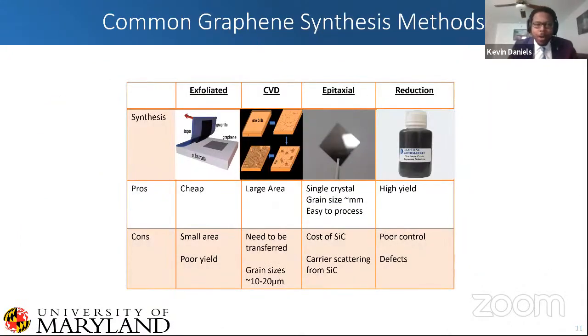Now, jumping over to graphene, because that's what we're using as a scaffold, there's a few different means of actually making this material. One is through exfoliation, which is definitely the cheapest way. Again, taking Scotch tape and peeling it from bulk graphite, and then you slam it down onto a substrate. But again, this is kind of random. You have these random flakes, so very small area and very poor yield.